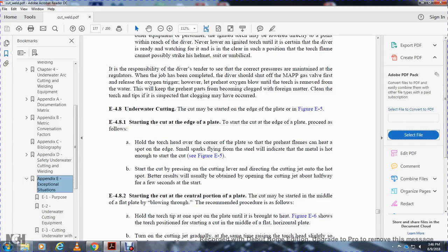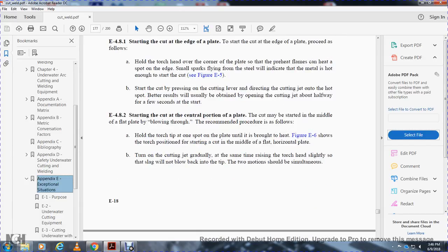E48, underwater cutting. The cutting may be started at the edge of the plate as shown in figure E5. E481, starting the cut at the edge of the plate. Starting the cut at the edge of the plate proceeds as follows. Hold the torch head over the corner of the plate so that the preheat flames can heat the spot on the edge, and the sparks flying from the steel will indicate that the metal is hot enough to start the cut. Start the cut by applying pressure on the cutting lever to direct the cutting jet onto the hot spot. Better results can be obtained by opening the cutting jet about halfway for a few seconds at the start.